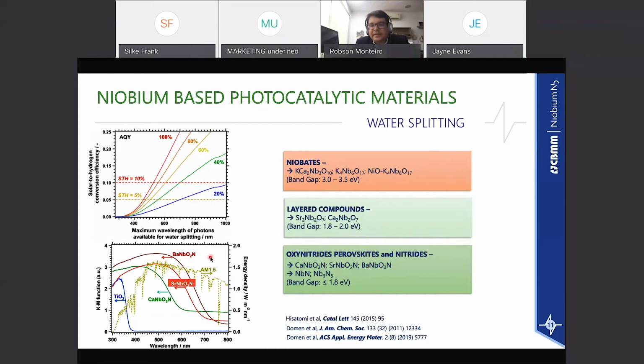And what would be the sunlight spectrum? What kind of light that comes from the sun will be the most efficient? We are trying to demonstrate here that there are at least three families of niobium-containing photocatalytic materials: what we would call niobates and layered compounds, and also oxynitrides and perovskites and nitride type compounds. Those materials are being developed in order to really change the band gap and shift those materials in order to catch photons from the visible light of the sun.